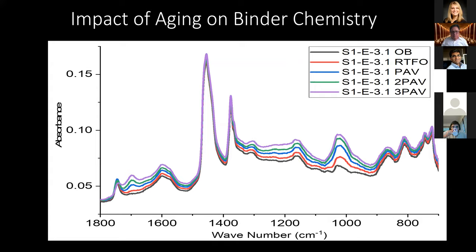One of the reasons that the FTIR is a unique characteristic that we may in Illinois utilize is the impact of aging can be seen in FTIR spectra. The black line is the original unaged binder, and as the binder is progressively aged, the absorbance increases, especially in the wave numbers that indicate oxidation. This increase can be used to quantify the effects of aging on modified binders.